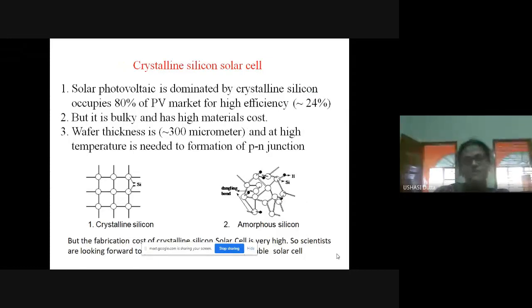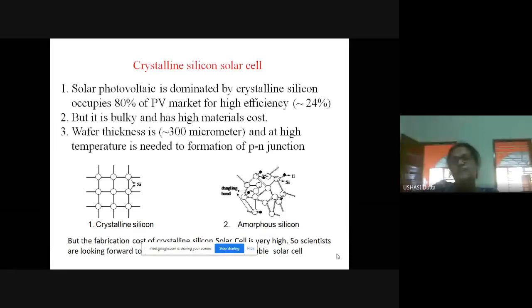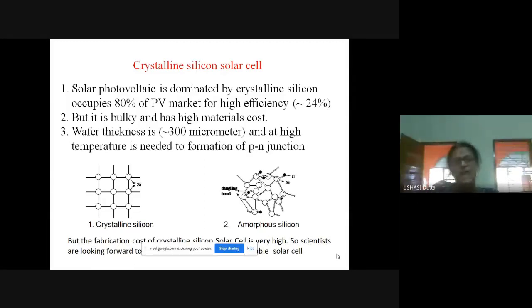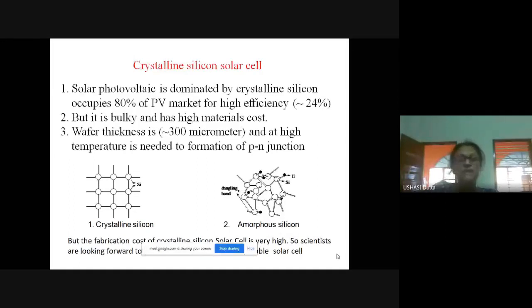This is the structure of crystalline silicon and amorphous silicon. The long range order is maintained in the case of crystalline silicon, and this is the amorphous silicon. Here, the unsatisfied bond is known as the dangling bond, and this is the defect density of the amorphous silicon solar cell. Actually, the solar photovoltaic industry is totally dominated by the crystalline silicon solar cell, which occupies 80% of the PV market, and the efficiency is 24%. But it is very bulky and has high material cost, its wafer thickness is 300 micrometer, and high temperature is required for the formation of the PN junction.